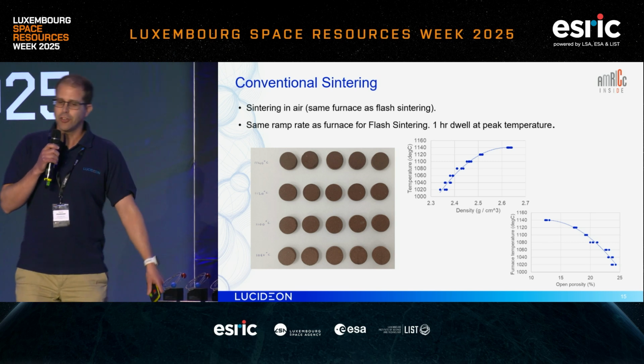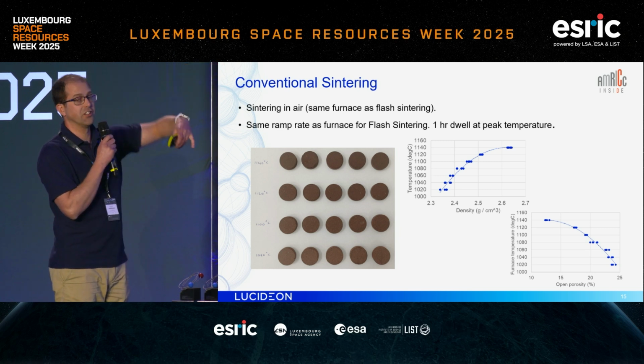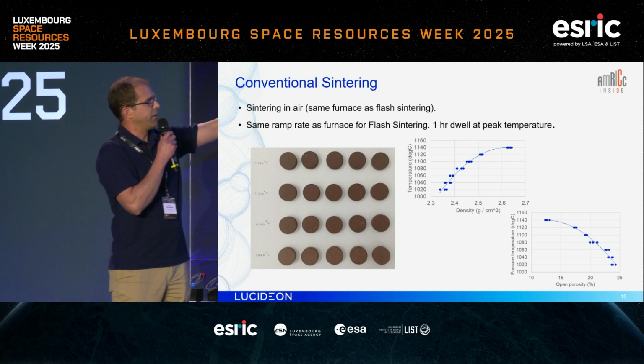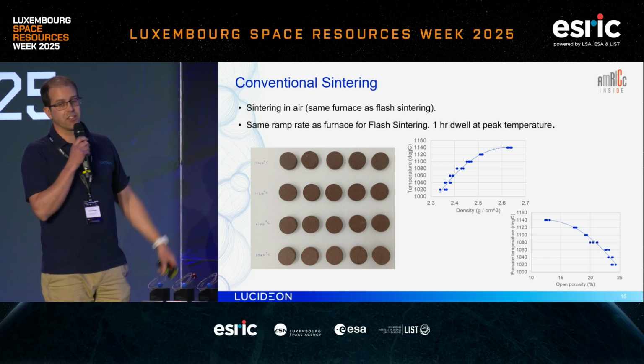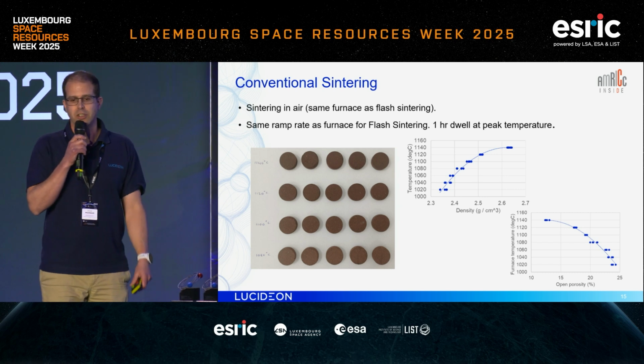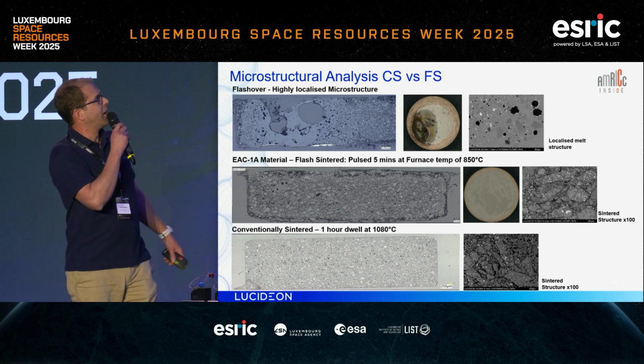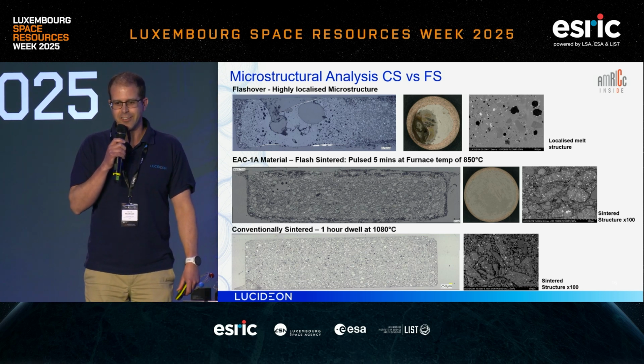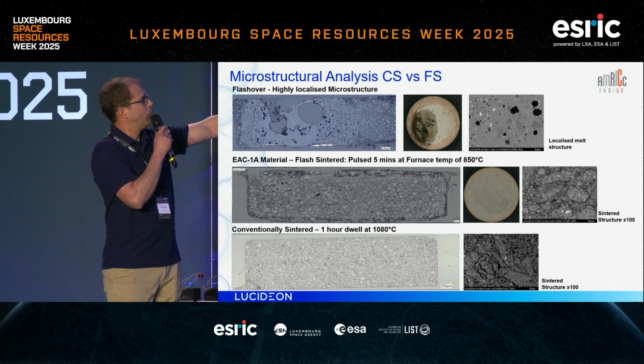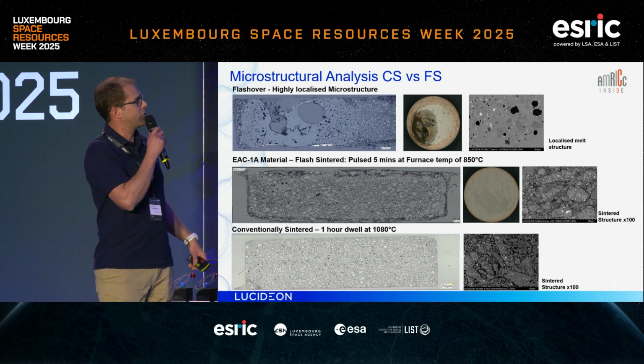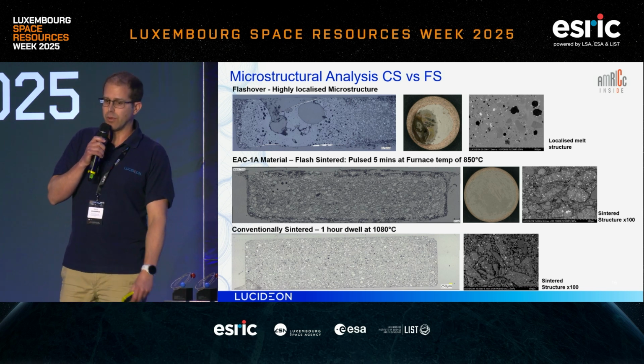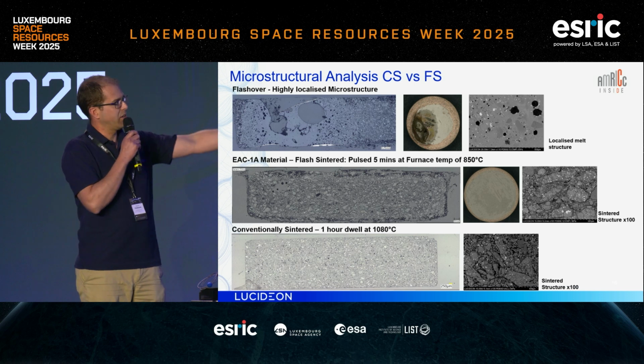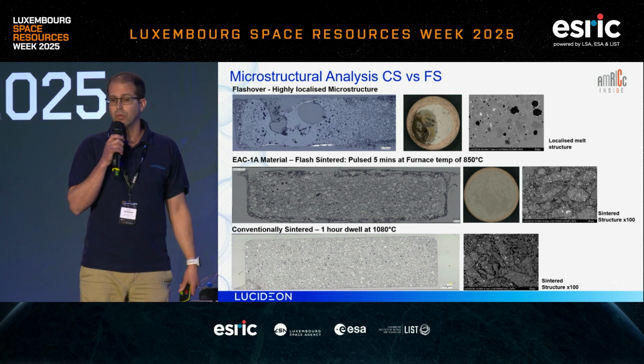Benchmarking against conventionally sintered samples, of course, is very important. So conventionally sintered in the same furnace, but with no electric field applied, at varying different temperatures. And then we would measure the porosity and density, and compare those with the flash sintered samples as well. So that's how we reached those conclusions. And then, of course, there was some microstructural analysis too. So you remember the fireworks video before on the top there? That's the melting of the middle and not touching the outsides, as is evident by the SEM images there. But then we have our simulant materials, both conventionally, 1 hour dwell at 1080, versus the pulse train method. And as I say, the densities that were measured were the same, but we do see a slight difference in the microstructures, and we'll discuss that in a minute.